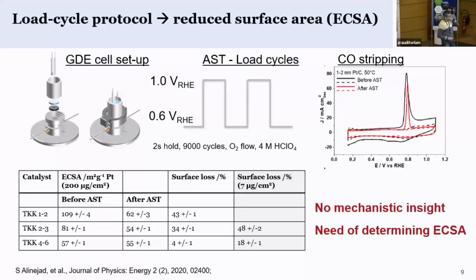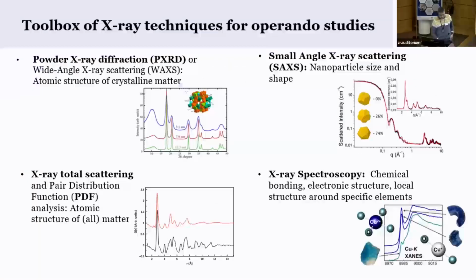And what you basically see after such a test, after the stress test, is that the surface areas are very similar. So even though you start with different surface areas, at the end you end up with almost the same surface area. However, this kind of test doesn't give you any information on what happens and why the surface area is lost. And that's, of course, where the X-ray tools come into play.